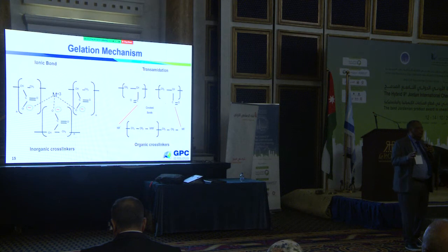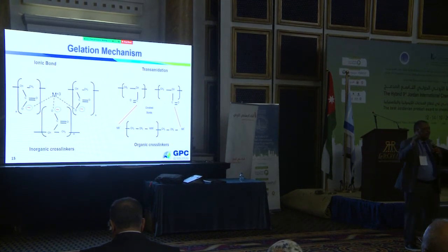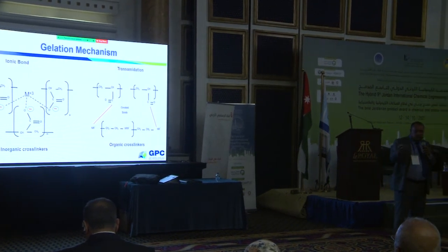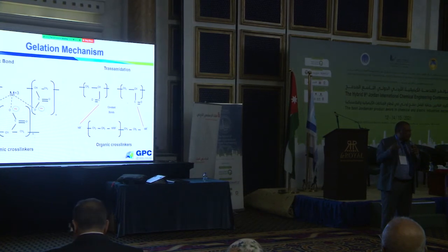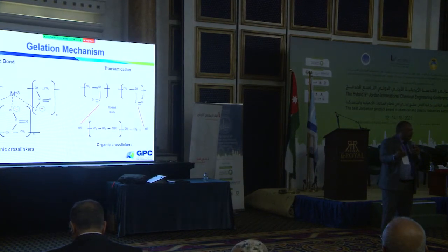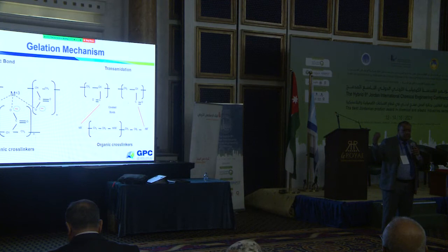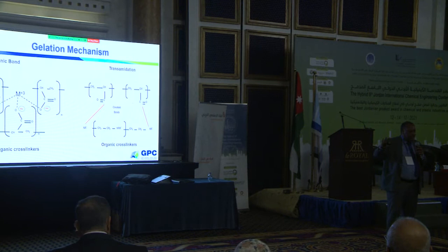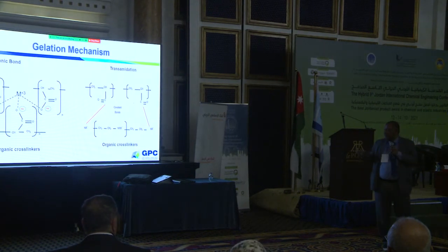Unfortunately, the organic crosslinkers can only work when the temperature is very high, above 90 degrees centigrade. So what about water production from zones that are low in temperature? In Qatar, for example, offshore in the North Field, the temperature is about 40 or 50, maximum 60 degrees. So such organic crosslinkers will not form a gel again. They need very high temperature.